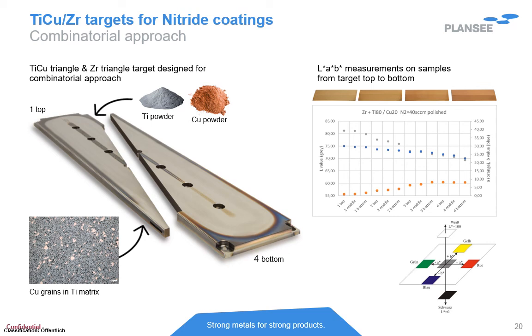If you look at the diagram on the right side, you can follow the decrease of the L value, these are the gray dots, with increased content in the coating. At the same time, the A value, standing for red, is increasing and the blue B value is decreasing. A very simple approach supported by the application of powder metallurgically produced targets.